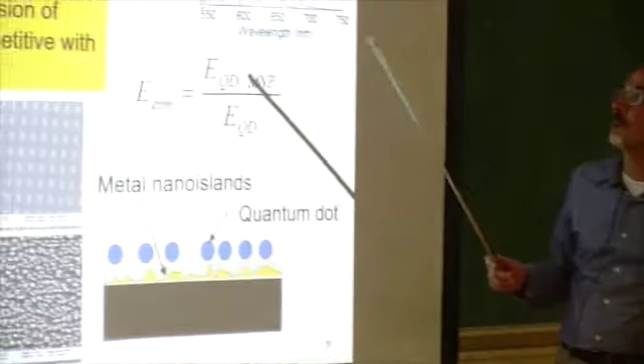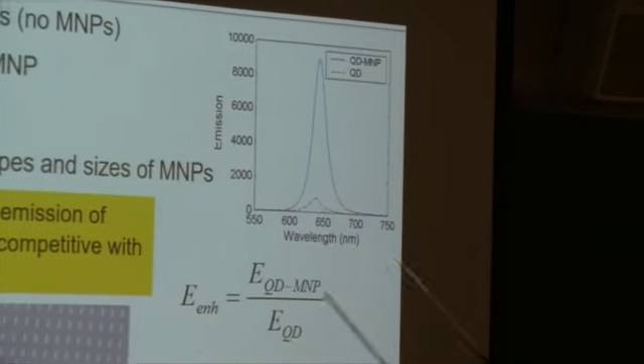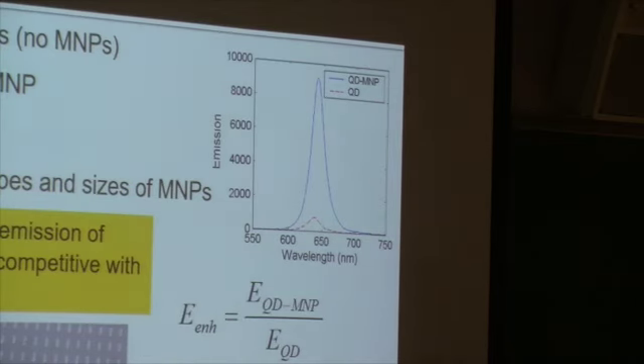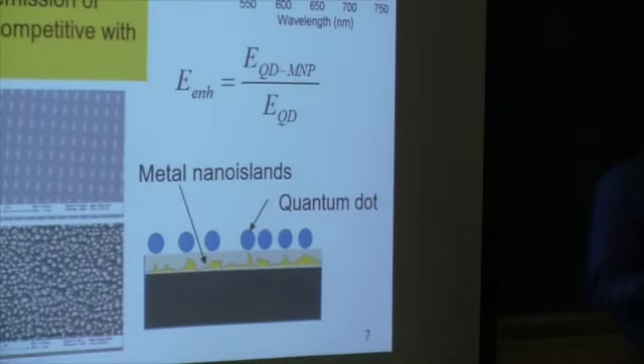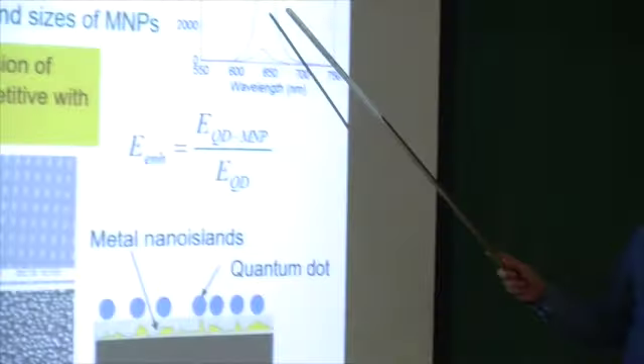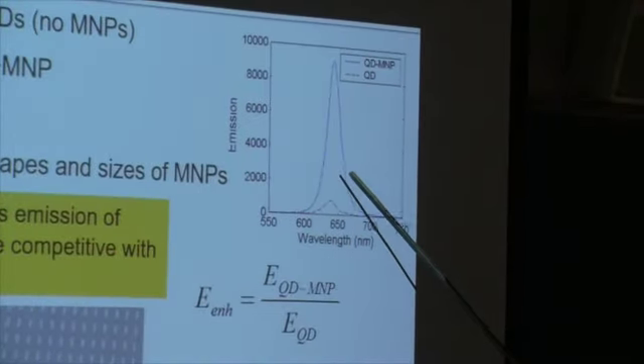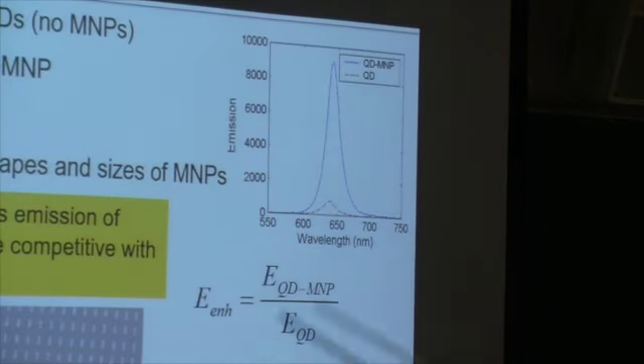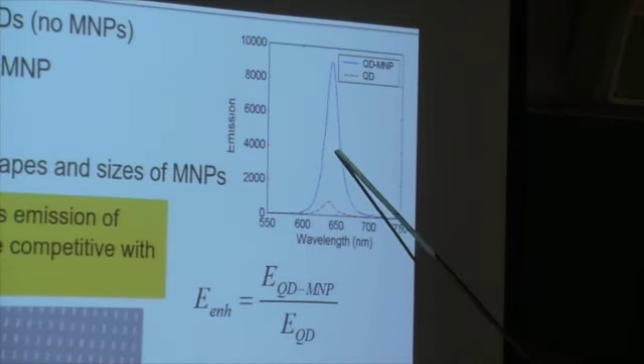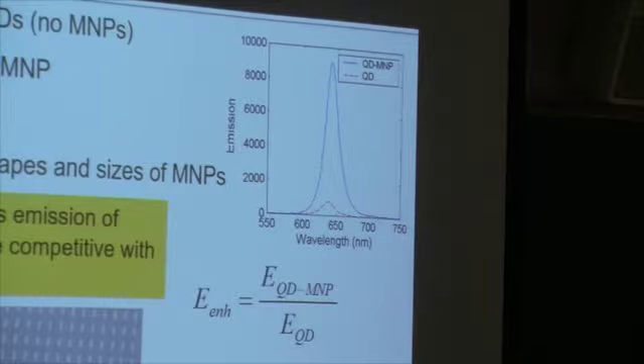So let me show you. This red line is the emission of the quantum dot right on the glass, and the blue line is the emission of the quantum dot on this structure. They are side by side and very tiny. What happens is that the emission of the quantum dot on the metallic structure is, I don't know, at least 10 times larger than the emission of the quantum dot on glass.